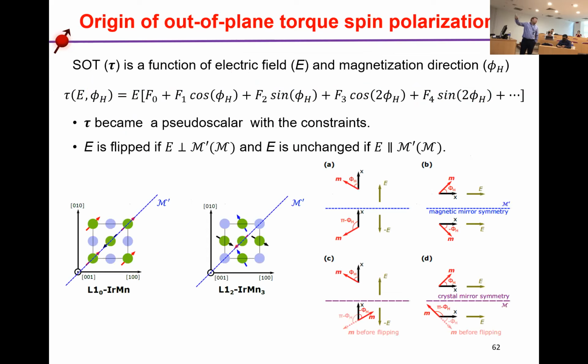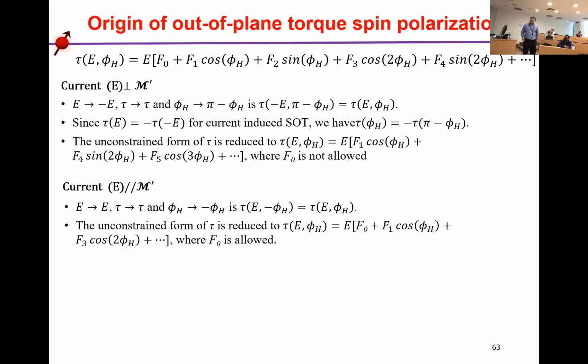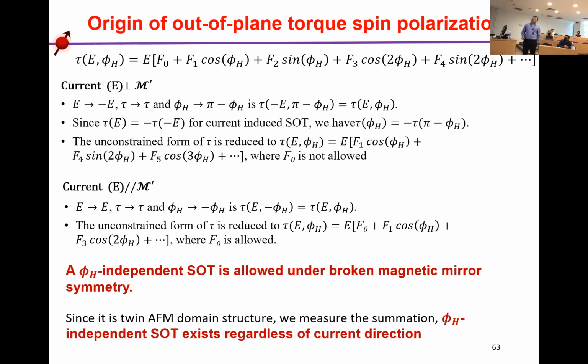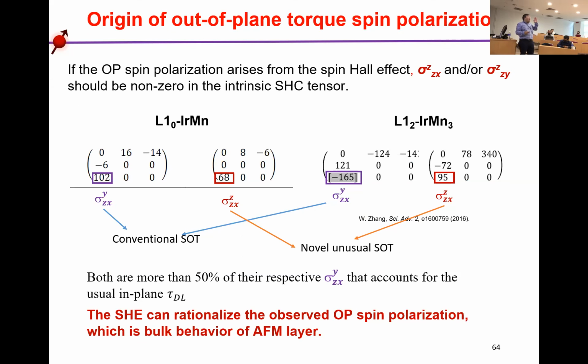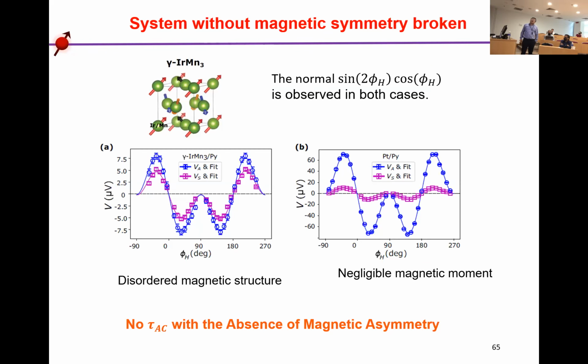And definitely you can do some analysis based on the symmetry. You can derive that this is really due to the magnetic asymmetry. We have also done the first principle calculation here. When the Néel vector is along the c-axis or along the a-axis, there is no perpendicular out-of-plane spin polarization component. But when we pivot the spin polarization, we show some out-of-plane spin polarization spin Hall conductivities. But for the L12, under both cases, the out-of-plane spin polarization exists. While for the randomly oriented gamma manganese, we did not see this out-of-plane spin polarization because there is no magnetic asymmetry.